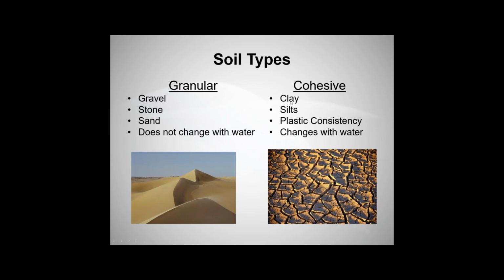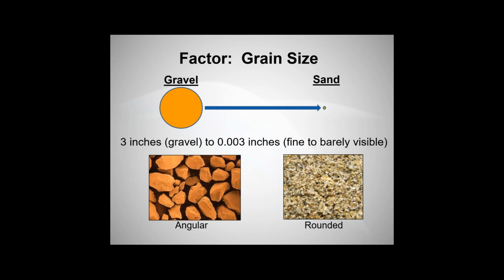Whereas in the cohesive world, you've got clays and silts. They tend to have a plastic consistency and they change with water. So in the grain size of a granular material, that can range from 3 inches down to just barely visible by the naked eye. Think about if this were an angular material, 3/4 inch or 1 inch angular material with fairly good porosity, we're going to be able to pump almost anything into that from a permeation grouting perspective, including the kitchen sink, right?